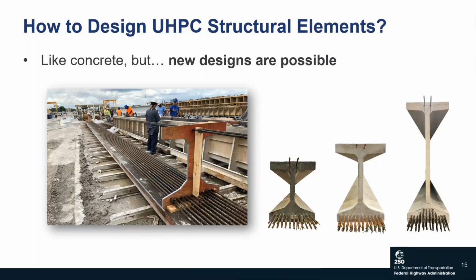The ones you're seeing here in the picture, the one on the left, and the first two. So the smallest one there is 32 inches deep, and then that one is 43 inches deep. Those were tested at Turner Fairbank. And then those are published. They were tested in flexure and shear. The deeper one, the 73 inch, we still have in the lab. We're planning on testing them within 6 months to a year.